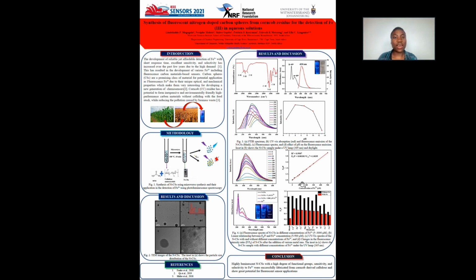Results were then utilized to plot a straight line with the concentrations ranging from 0 to 500 micromolar. The limit of detection calculated using this line was obtained to be 70 nanomolar, which is comparable to previous studies.